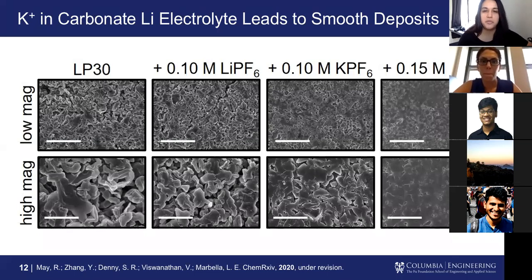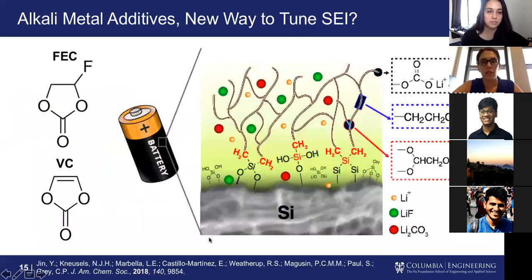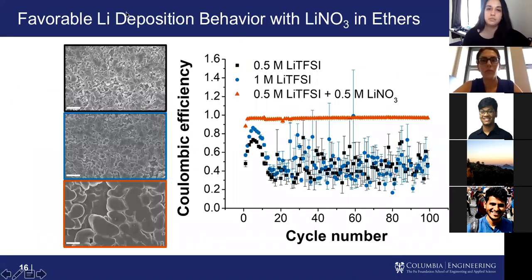Okay, and then this is a few slides forward, but in regard to ether, does that increase polarization during these tests? It depends on the electrolyte. By increased polarization, I think that means increased overpotential. I don't think the overpotentials are increased so substantially. I think the overpotentials are similar to carbonates, where the overpotential for the current densities that we're running is about 0.1. It may be a different scenario if you use a higher current density, for sure.